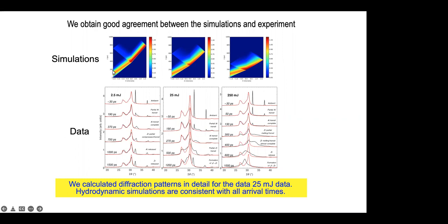And so we have this roughly 100 to 200 picosecond duration pulse that comes in at the ablation plane to the aluminum, and then that launches a shock wave into the aluminum, which then is reflected somewhat at the zirconium, and then because of the impedance matching between zirconium and aluminum, a 30% or so higher shock pressure is launched into the zirconium, and then that propagates through.